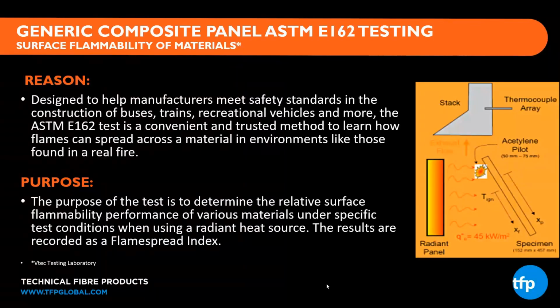There's a radiant panel that's giving off an amount of heat and also an acetylene pilot flame that is hitting the backside of your sample, which is in a 30-degree vertical position. So what we're really looking to do is measure how far that flame runs from the pilot down your specimen. So the purpose is to determine the relative surface flammability performance of different materials under these conditions. The results are recorded as a flame spread index. Next slide, please, Neil.